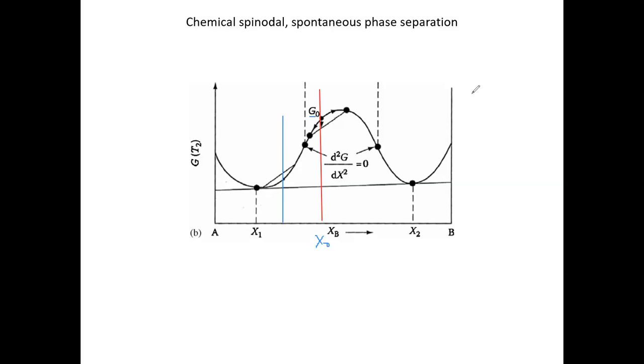Why is that? Well, consider what is happening during the spinodal decomposition. Initially, what you have is just a homogeneous mixture of A and B atoms with average composition X naught. But as we already know, the concept that we're always going to have fluctuations is very familiar, because the atoms are always moving around. So maybe at some point you have a fluctuation such that in one region of the system you have a slightly lower composition, and in the other region you have a higher composition. So you have X naught minus and X naught plus, indicating a fluctuation that leaves you with two locally separated regions with different compositions.